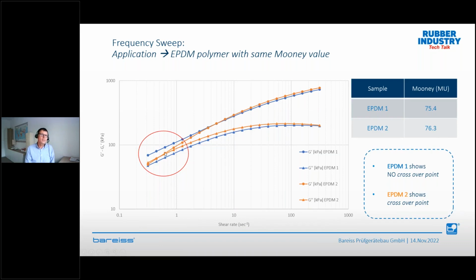So you see on the orange one, you have this crossover point, which indicates molecular weight, at this position. And on the blue one, you have to go to a much lower shear rate. The crossover point was out of the graph, on the left side. So there is a huge difference in the structure of these two polymers.